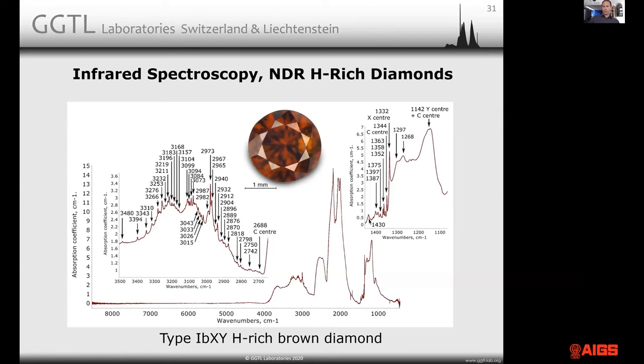And if it's somewhere in between, then you have a mix between Y center plus C center. In all cases so far that I've seen, you always see a little bit of C center. And you can see the C center in this spectrum with the peak at 1344 wave numbers, and in front here in the near infrared at 2688 wave numbers.